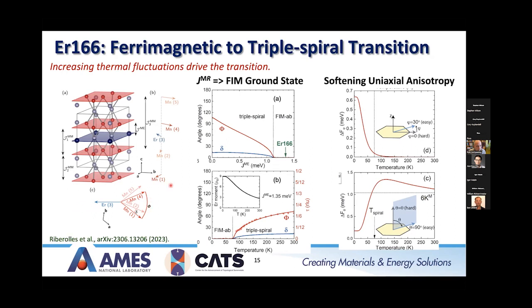So we looked at this in more detail with mean field theory. For this, we transferred some of the parameters over from the terbium 166 study we did, and we also had some input from some erbium 166 inelastic neutron scattering data. Basically, based on the coupling parameter we found, we were able to show that it's consistent with the erbium-166 having a ferrimagnetic ground state.